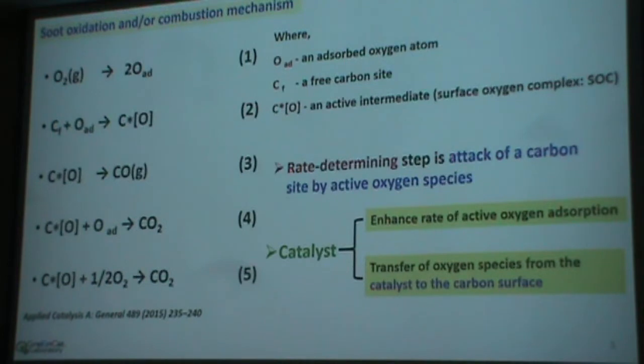In the soot oxidation reaction, the active formation of carbon-oxygen intermediate species is important, and that is considered the rate determining step. So how is the catalyst playing a role? It enhances the rate of active oxygen adsorption and enhances the contact between carbon and oxygen, which leads to enhancement of the rate of reaction, and it also helps in the transfer of oxygen species from the catalyst to the carbon surface.